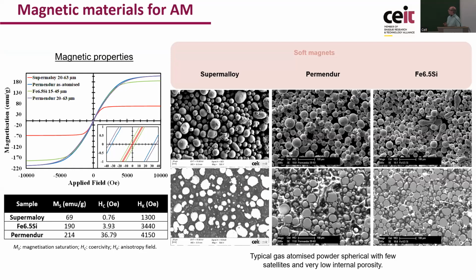Iron silicon is quite convenient because it's a cheap material. It has a saturation magnetization around 1.7 Tesla, which is high enough, and the coercivity is as well quite low. We did some builds with iron silicon, but the point is that the silicon content is quite big. It reduced the ductility of the material, and during selective laser melting, there are quite significant thermal stresses. The material was brittle, and we could not easily avoid the formation of cracks during the deposition. So finally it was discarded as well.